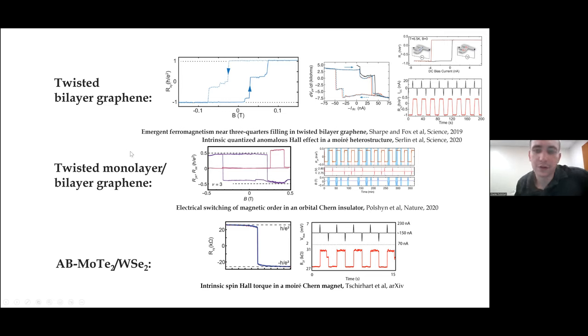In twisted monolayer bilayer graphene, we saw that small excursions in electron density or in chemical potential can flip the magnetization as a result of the population of these chiral edge states with additional electrons and the coupling of that to the total magnetization. And in this molybdenum telluride tungsten selenide system, we've seen how electrons that enter the bulk have anomalous velocities they pick up from the Berry phase, from the Berry curvature, and accumulate on opposite sides of the device, and thus flip the magnetization.